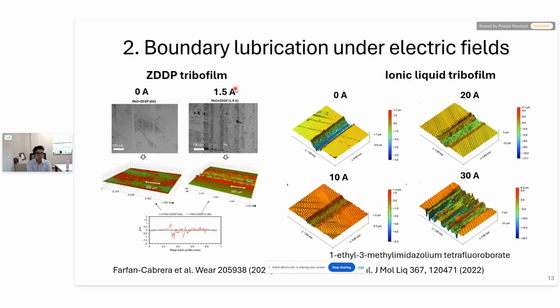There are studies on ionic liquid tribofilms as well, where initially the application of some electric field has been shown to promote tribofilm formation. But when electric fields are further increased, the tribochemical reactions are suppressed, and instead, significant wear of surfaces is observed. And there are multiple other studies. These are just a couple of studies I picked from the literature. Multiple studies show electric fields affect tribofilm formation and their frictional and wear properties. However, the fundamental mechanisms by which electric field affect reactivity still remain not very well understood. And moreover, it is extremely challenging to model mechanochemical reactions in the presence of electric field. So we need to develop a better understanding of the mechanisms of these reactions.